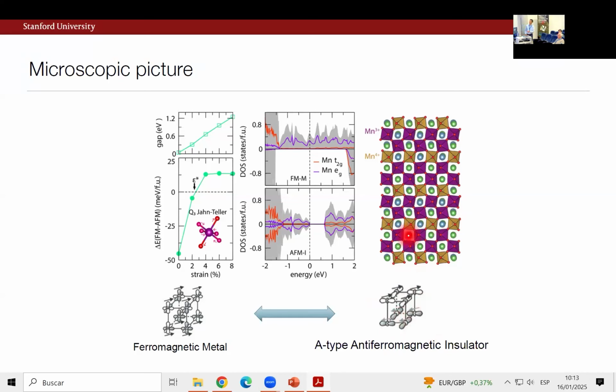So the notion is that this is kind of the specific manifestation of these sorts of patterns in terms of the density functional theory that my colleagues had done. But just to describe a little bit without going into the details, this is a difference in energy between the metallic state and the insulating state. And surprisingly, at least within the sampling, the crossover strain is fairly close to what we see experimentally. And so what you see here is the gap for the antiferromagnetic insulator, right? It keeps going up. And the point is we hit a metal insulator transition when this phase becomes more overall energetically favored than this phase, okay?